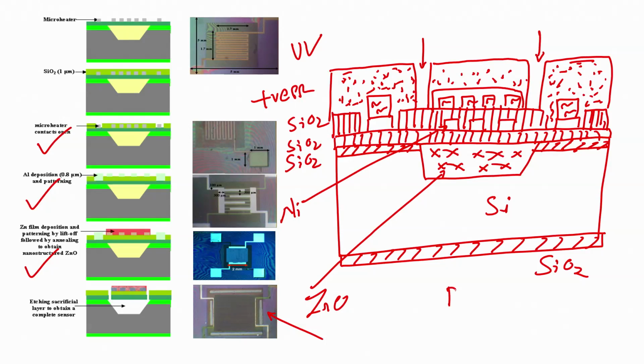We will dip this wafer in BHF. When we dip this wafer in BHF, what will happen? We will have access to our sacrificial layer, right. We can now see the zinc oxide because we have etched with BHF. We have etched silicon dioxide using BHF, right. So, after creating a window, I have dipped the wafer in BHF, which is buffered hydrofluoric acid, which will etch my silicon dioxide. And after I etch silicon dioxide, I can see zinc oxide through this window.